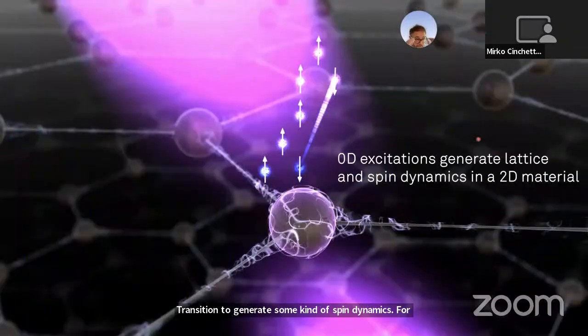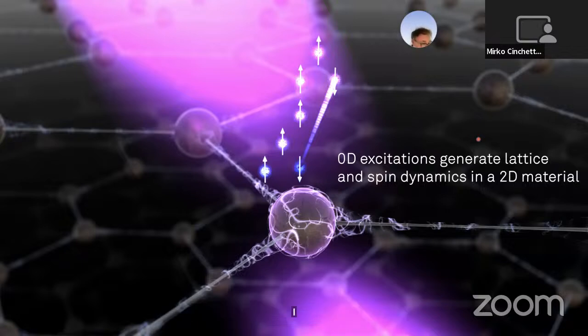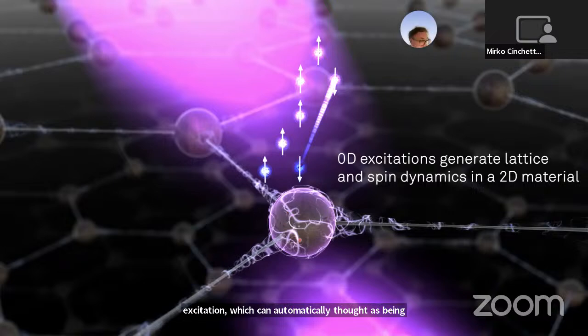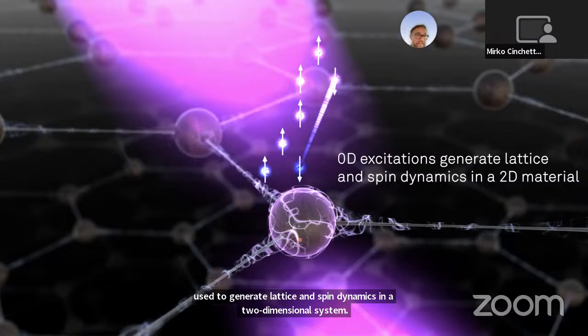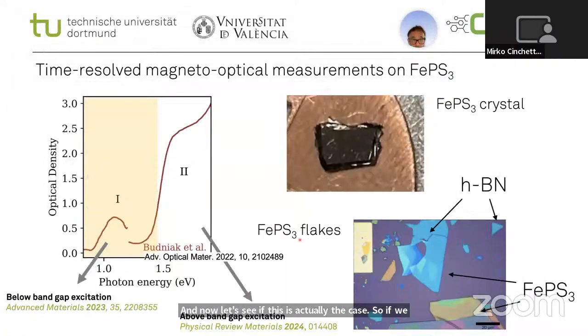So this is actually what I find exciting about iron PS3. It hosts this kind of excitation, which can ultimately be thought of as being localized on a single iron 2+ ion. And these are basically zero-dimensional excitations, so localized on an atom, but that might be used to generate lattice and spin dynamics in a 2-dimensional system. And now let's see if this is actually the case. I will start with the magneto-optical experiments.